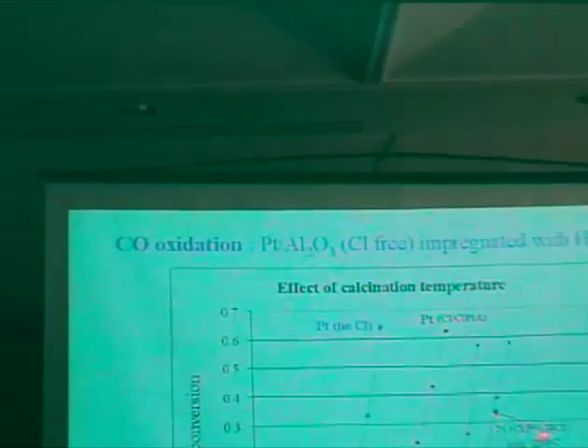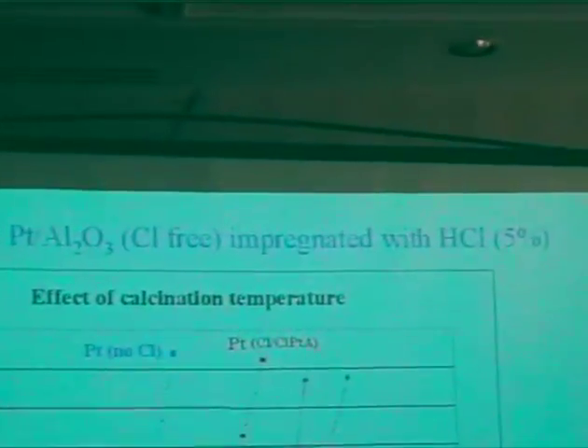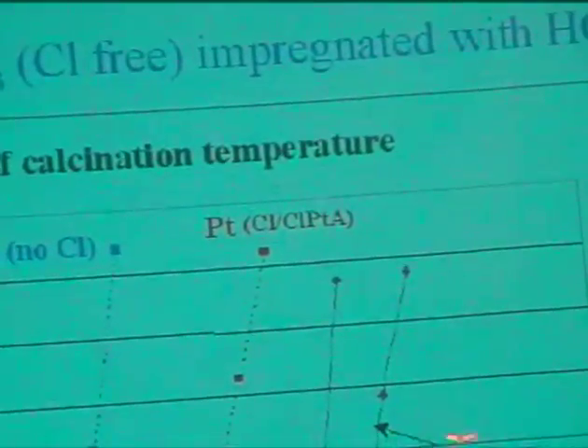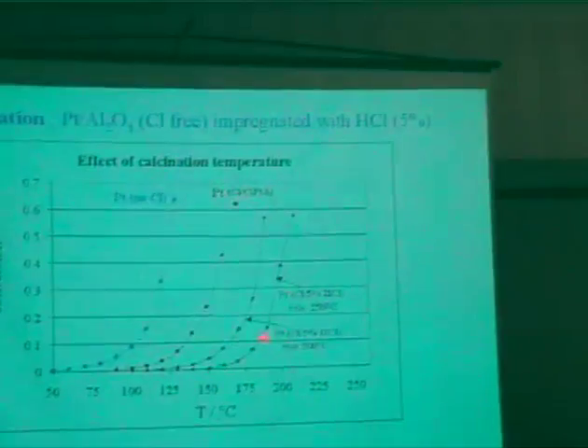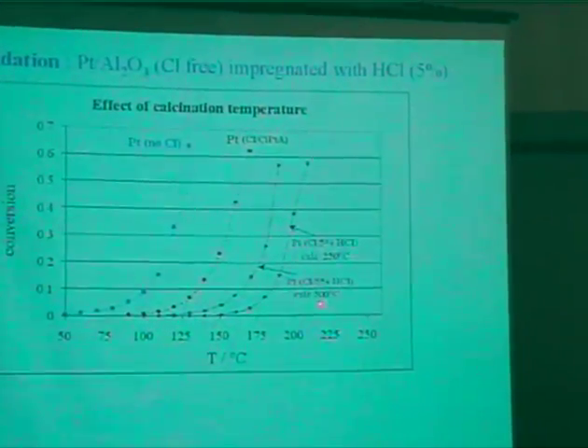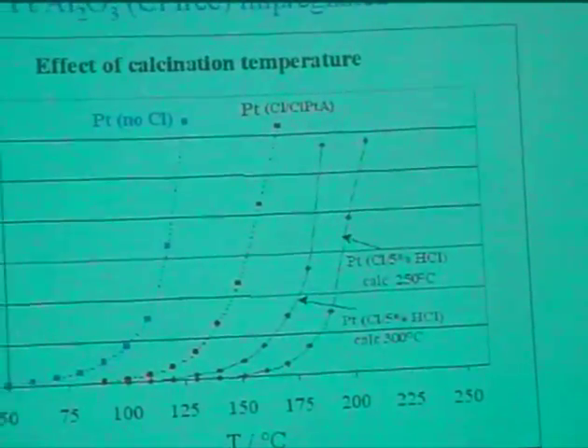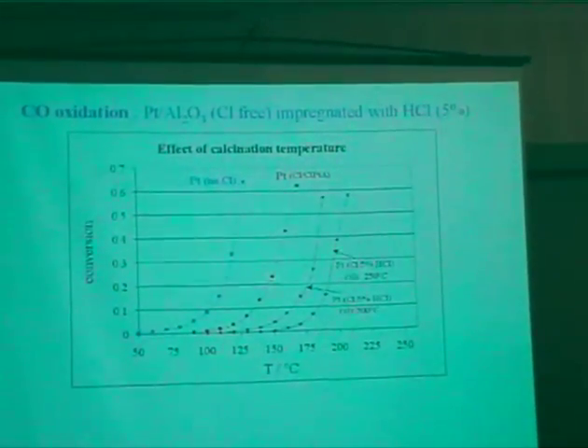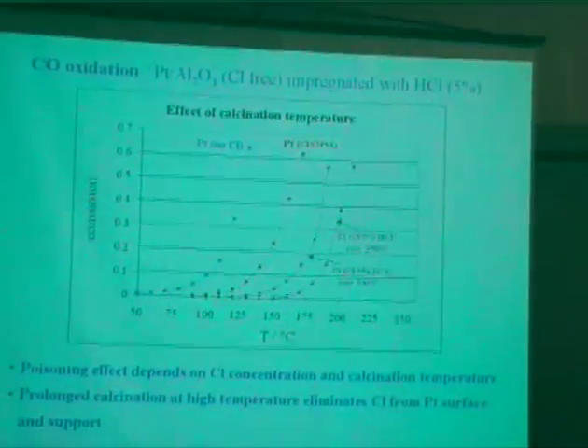Now, if we do the same thing with an excess of chlorine, now with 5%, the other one being stoichiometric with the amount that we used in the preparation, and calcine at 250, then we have a very significant difference in these rates. I didn't even calculate that. But if you go back, then it starts getting better. If you go back on your calcination treatment, at a little higher temperature, it starts getting better, and eventually you end up with this same line because the chlorine is coming back and forth and eventually out of the reactor. So you can clean the surface eventually by subsequent pretreatment.